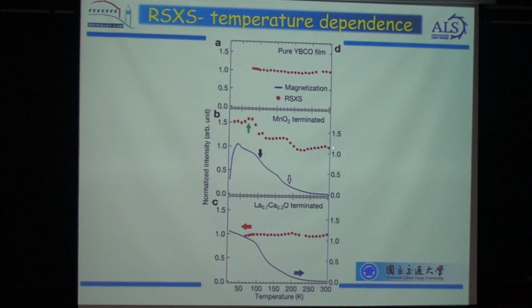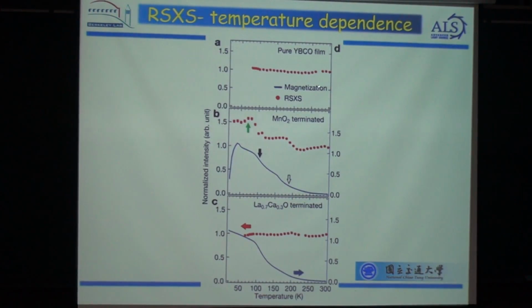And later we see that for this bilayer termination, when the temperature is going down, you will see some increase of this signal, which means that in this system you have some new order happening with the decreasing temperature. We can do the same experiment in the pure YBCO, and you will see nothing changed with the temperature.